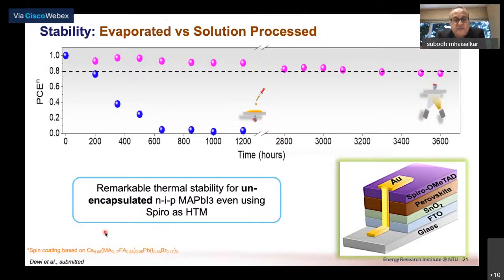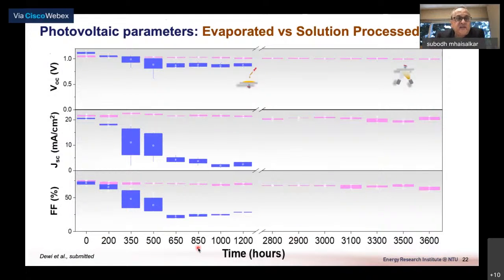So this stability of the NIP, methyl ammonium lead iodide, is also notable because we are using Spiro as a hole transport material. Spiro has been known to cause degradation in solar cells from a stability perspective as well. This material that I am showing you in terms of its degradation is a multi-cation perovskite, and we really did also want to just rule out any other factors.